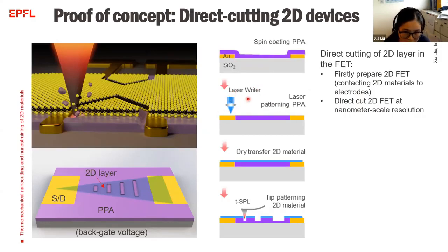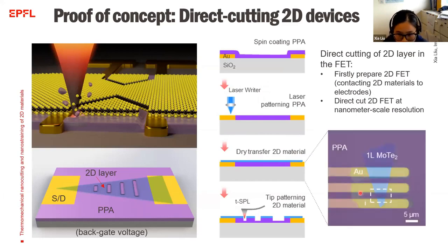Actually, as I mentioned before, the laser writer is one component in the NanoFrazor tool. Then, without the PPA on the electrode, we transfer the 2D layer on top of the PPA, with two ends in contact with the source and drain electrodes. Here is the device image. You can see this color represents the PPA, here is the yellow gold, and here is the monolayer MoTe2 flake. And at the end, we are going to use the hot tip.